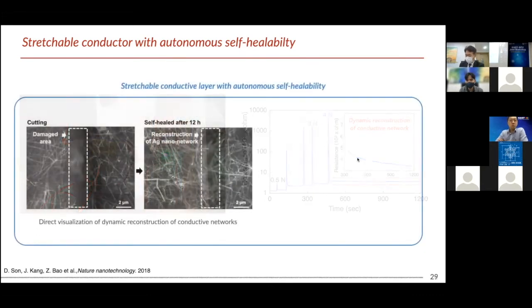To visualize what's happening here, we perform the SEM measurement. So upon the damage, initially because of their insulating properties, we couldn't visualize the nano network in this damaged area. But after 12 hours they start to reform the wall of the network and become very conductive. Then we start to visualize this damaged interface, meaning that they truly dynamically reconstruct their network over time.